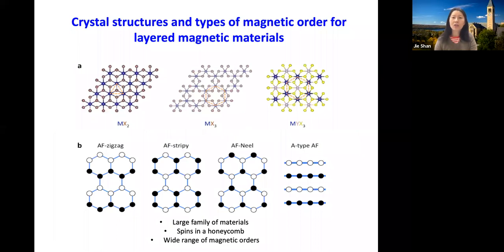It turns out that there is a very large class of crystalline layered materials that are magnetic. I'm just listing a few here, and the schematic at the bottom shows the magnetic ordering. The spins, those blue balls, are mostly in a honeycomb structure. The white and the black are spin orientations in opposite directions. It could be out of plane, perpendicular to the sheets, or in plane. So you can have a wide range of magnetic orders: antiferromagnetic zigzag, stripy, Néel, or A-type antiferromagnetic, with one layer along one direction and another layer along a different direction.